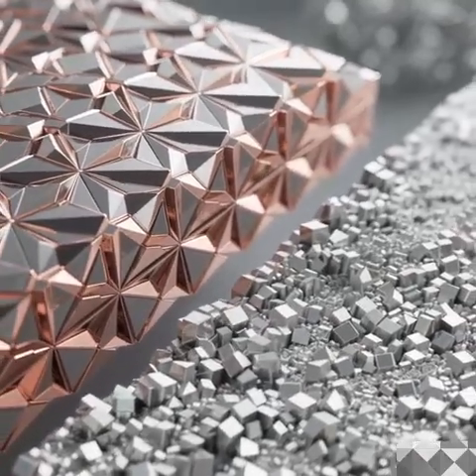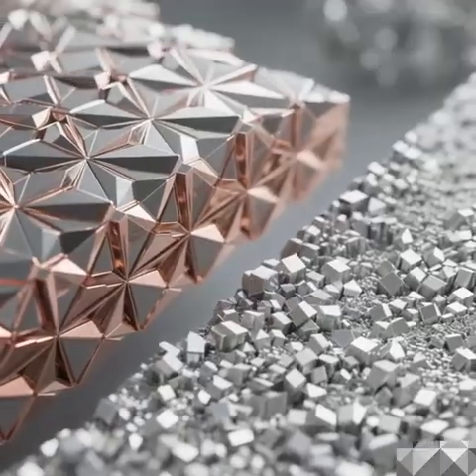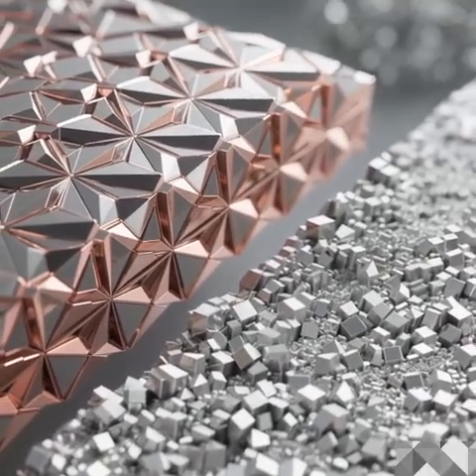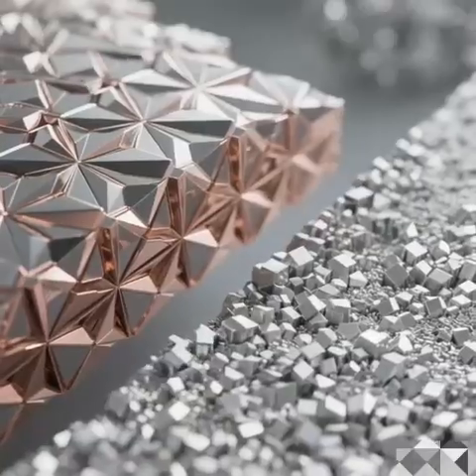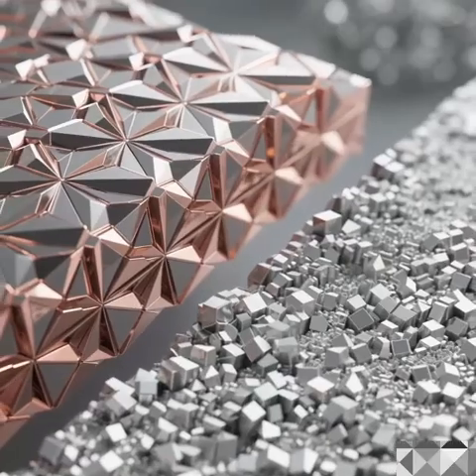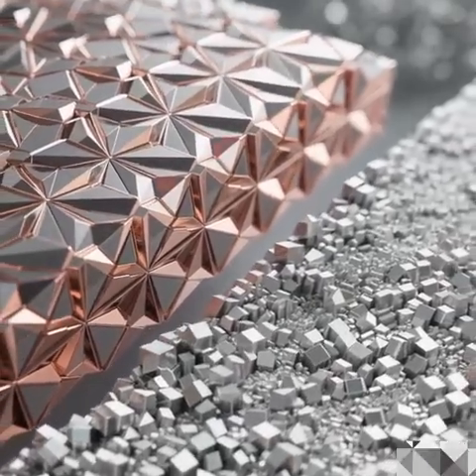Well, the thin NCC layer on top, with all its grain boundaries, that's what initiates the bond. It promotes rapid grain growth right at the interface. Okay, gets the connection started quickly. Exactly. But the magic is in the thicker, coarse-grained layer underneath.